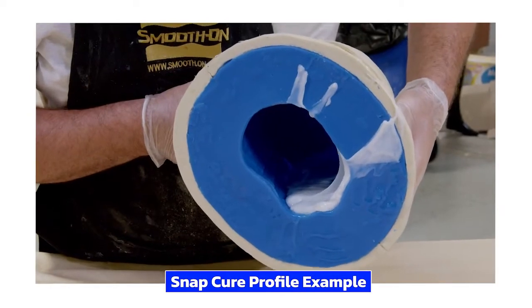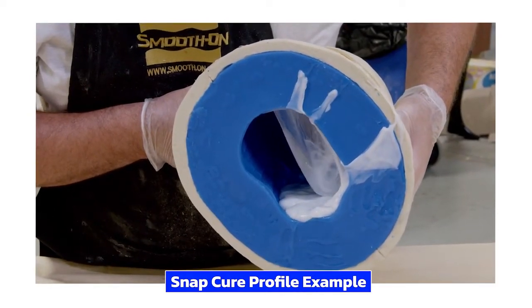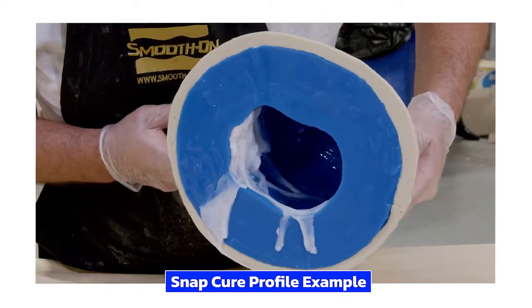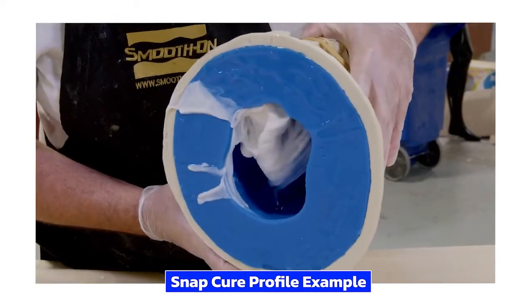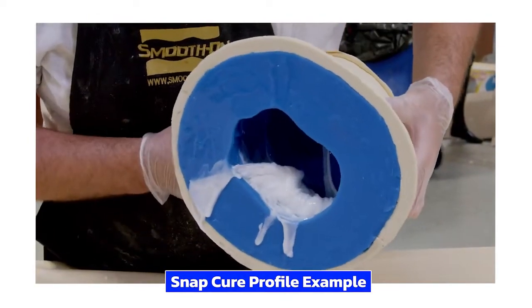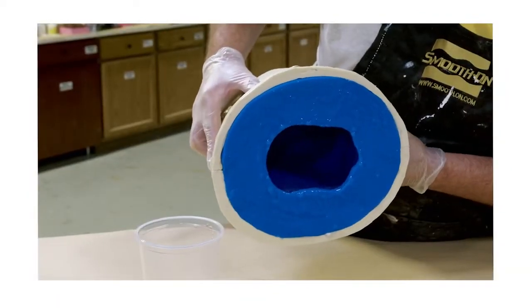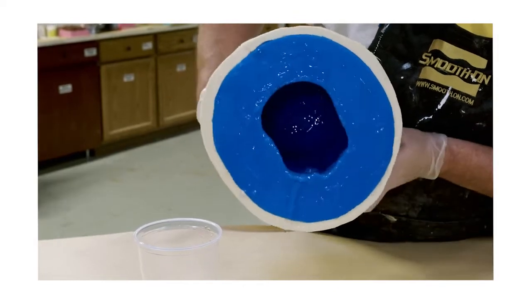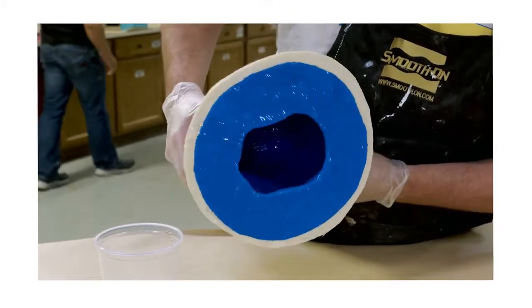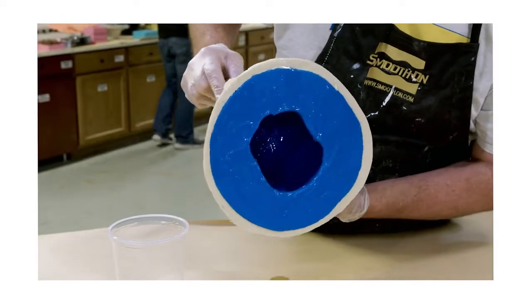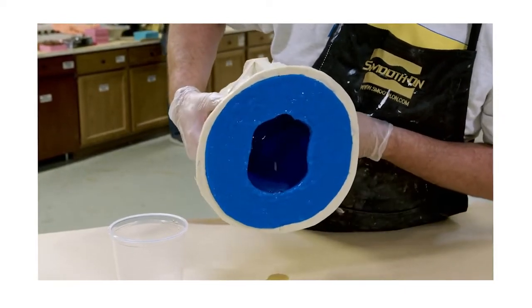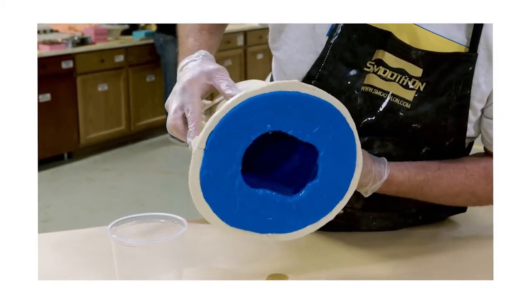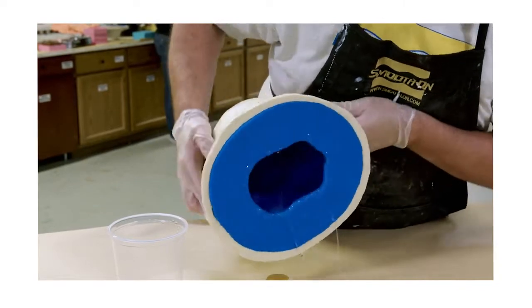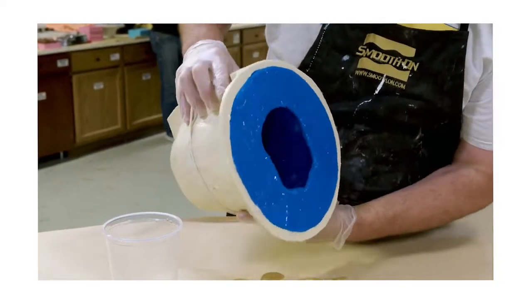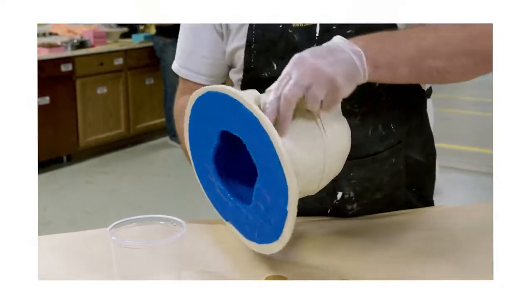This means that if we have too much material in the mold slumping around and the material working time expires, it's going to set up and create a thick area in our casting. To avoid this issue, we recommend to add just enough material to the inside of the mold so you can cover the entire inside, but not have too much material slumping around, so that when the material does set up, the inside of the mold is evenly coated and gives us an even thickness throughout our casting.